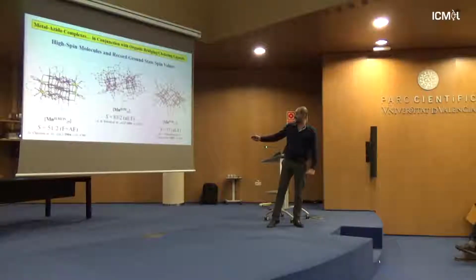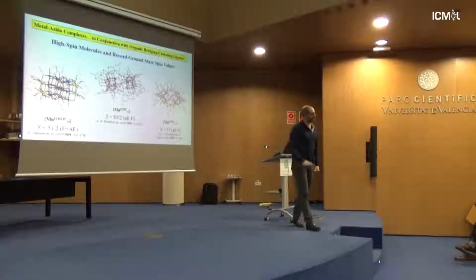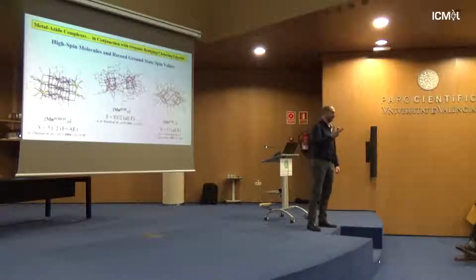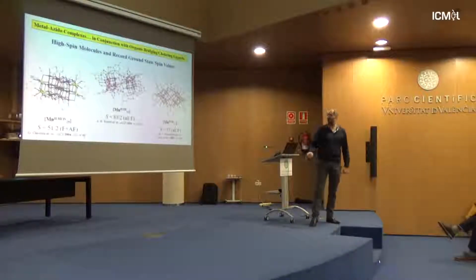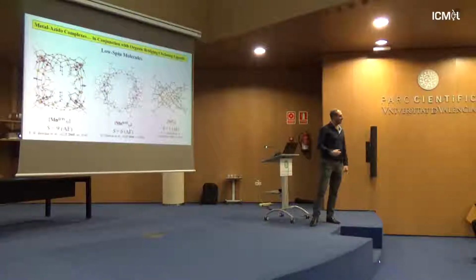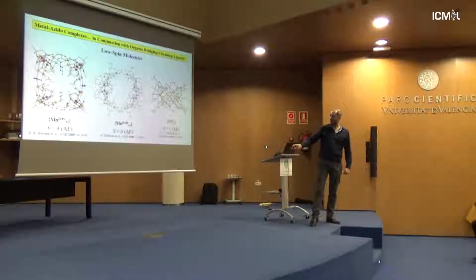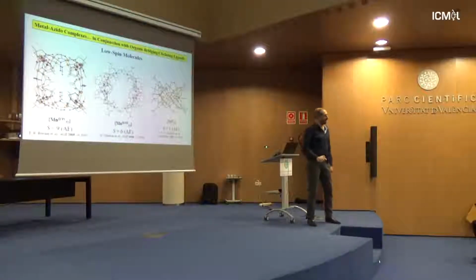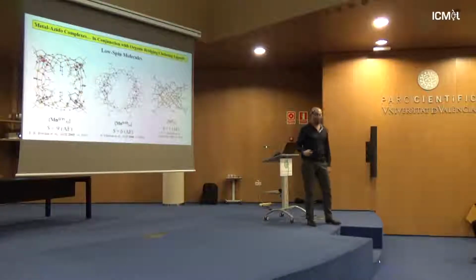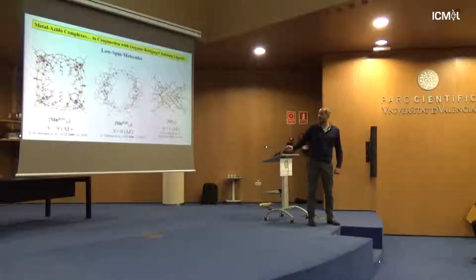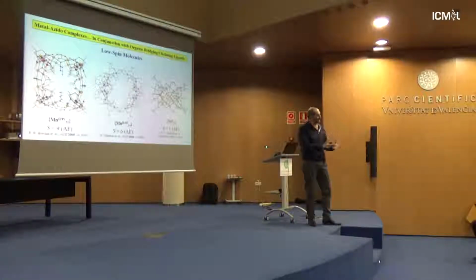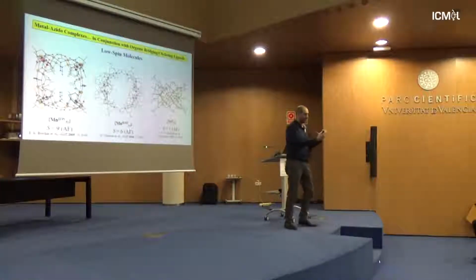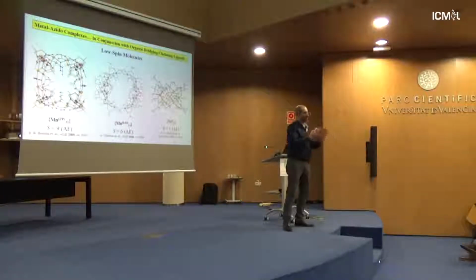Now, regardless, somebody could say that this is a very successful or a little bit guaranteed route. It could be. But at the same time, looking in the literature, you find compounds like this, which are still high nuclearity compounds. They still have end-on azides, but look at the spin, very low. Antiferromagnetic interactions are predominant on those species, opposite to the interactions here, which means that this is not really a guaranteed route.